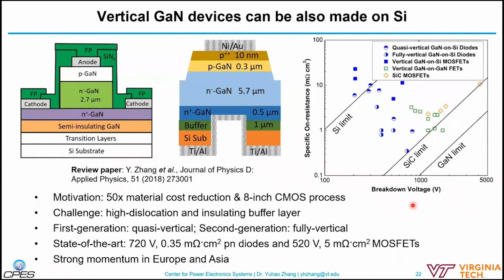Okay. So it should be noted that this vertical GaN device can not only be built on the GaN substrate, but also on very low-cost silicon substrate. There are a couple of different ways to build these devices. The very early device is called a quasi-vertical device, which means one electrode is on the front side of the wafer, and the other is built on a deep mesa. Very recently, a more popular way is using a fully vertical structure, by selectively removing the silicon substrate and the insulating, very defective buffer layer. So there are a lot of trenches on the backside, like some MEMS systems.